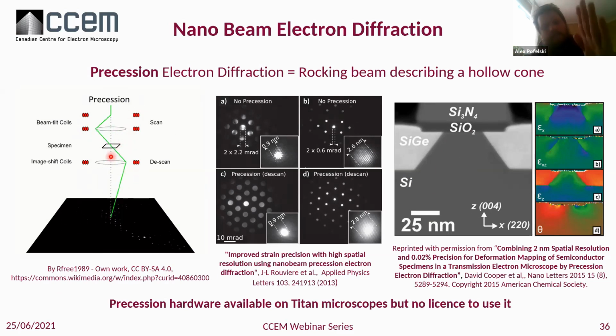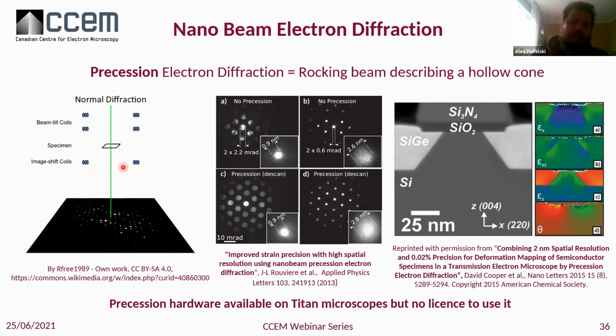So you are exciting different orientations of your diffraction at the same time. And if you can imagine this, the precession mode is done very fast, like 100 hertz, 100 rotations per second. So what you collect at the end is this new pattern that has a different intensity distribution because of this different beam tilt excitation. And you have here a very telling example of what the precession is bringing, and again, this connection between experiment and processing.